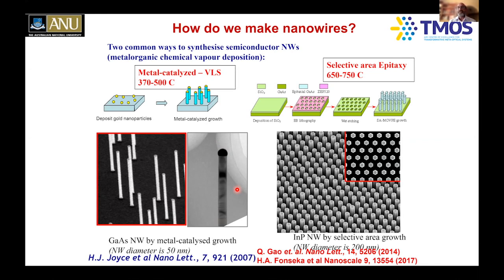The second technique which we use does not use any metal nanoparticles. We call it selective area epitaxy. In this case, we deposit some silicon dioxide on top of a semiconductor, put some photoresist, do electron beam lithography, and create patterns of holes. We transfer those holes through the silicon dioxide so that the semiconductor is exposed in those holes. I'm giving an example of indium phosphide. Then we put this into the MOCVD reactor, heat it up to 650 to 750 degrees Celsius, and introduce the gases needed for the growth of indium phosphide, trimethyl indium and phosphine. These gases dissociate, and then crystal starts precipitating out in the holes which you've created.